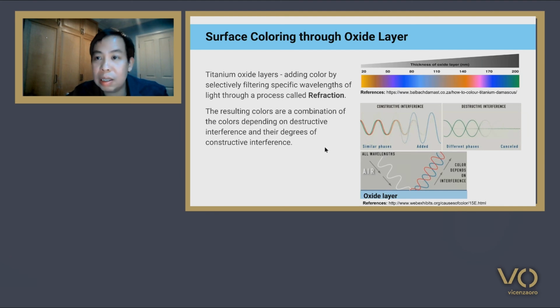This could be of a lot of interest to some of the audience as well. We do a lot of surface coloring of the oxide layers, and this is called anodizing. The color could be selectively filtering specific wavelength with respect to the thickness of the oxide layer. This is a refraction process, but the colors are actually very unique. And some of the colors here, you would see it's ranging from yellow, orange, purple, pretty much the rainbow color all the way to green.